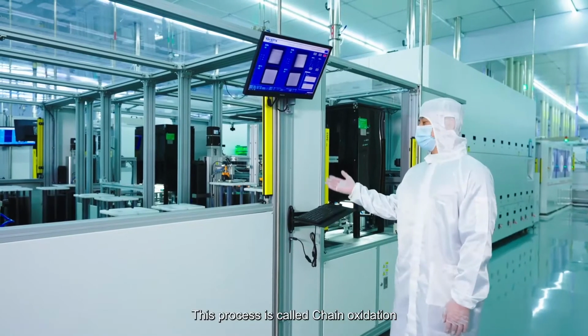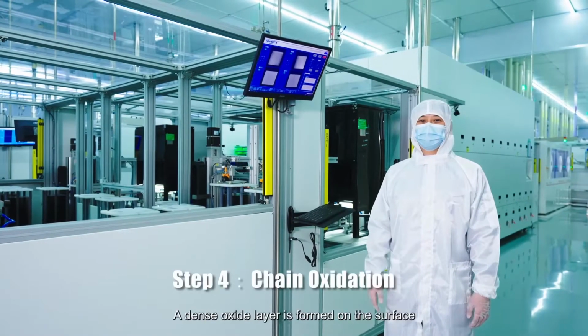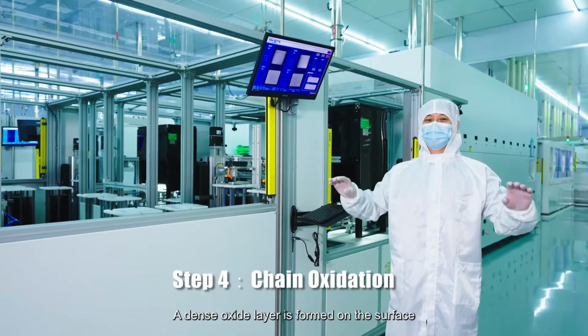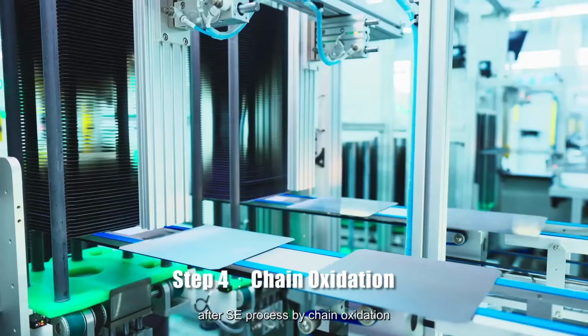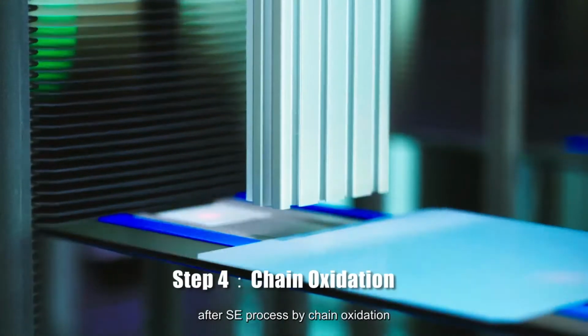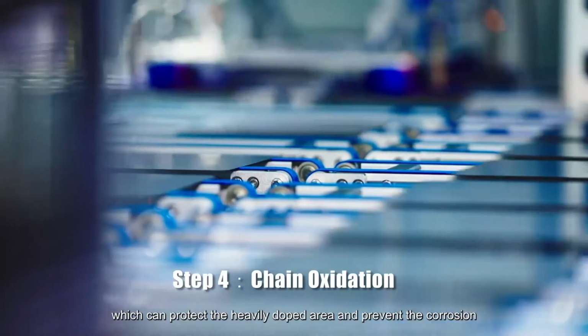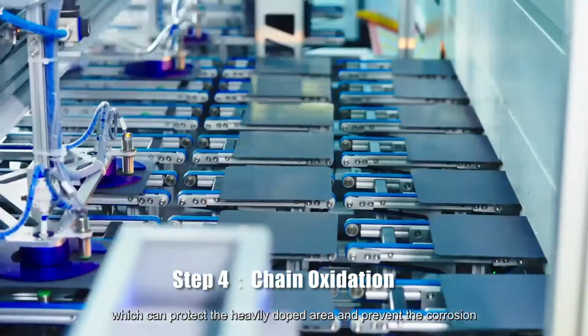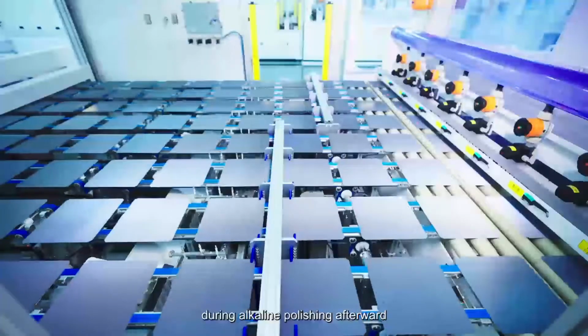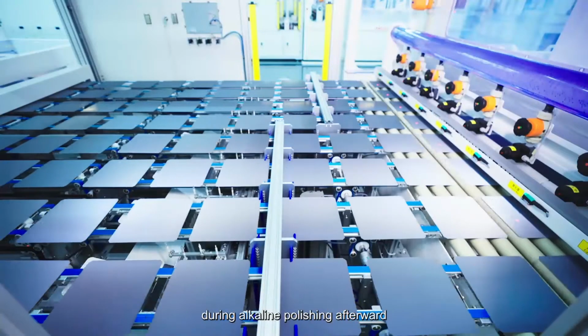This process is called chain oxidation. A dense oxide layer is formed on the surface after the laser process by chain oxidation, which can protect the heavy doped area and prevent the corrosion during alkali polishing afterward.